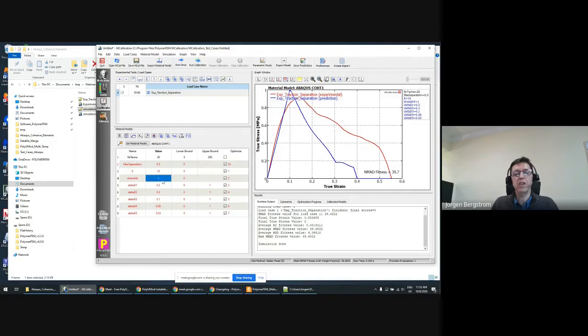The stress initiation is where this stress starts to fail. The material starts to fail. This is too high. One can argue that the initial response is linear elastic, and then it starts to soften here. So the actual onset of damage should be around here somewhere. If I click with the mouse, it says 0.66 here. So I'm going to make the stress init 0.66. And then I run one more time, and it looks a little bit like this now. But we can let the software figure out what this value should be. We don't need to do that.